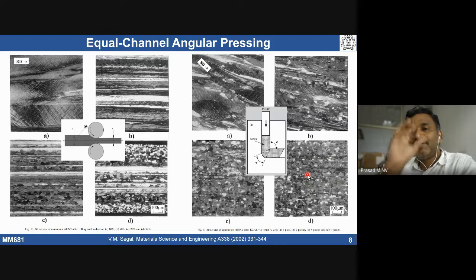That is basically what we are doing. After the fourth pass in route A, we'll get an almost equiaxed grain structure. Initially we started with a coarse grain of about 100 micrometers, and now it became a fine grain. Here in rolling we see a lot of elongated shear bands, many deformation bands in the elongated microstructure from uniaxial deformation. Here we are shearing, and because of the shearing activity we are refining the grain size of the material.